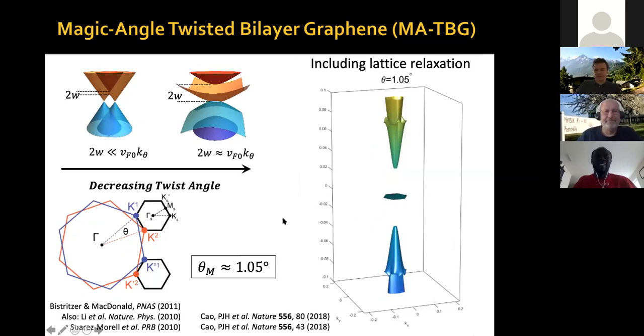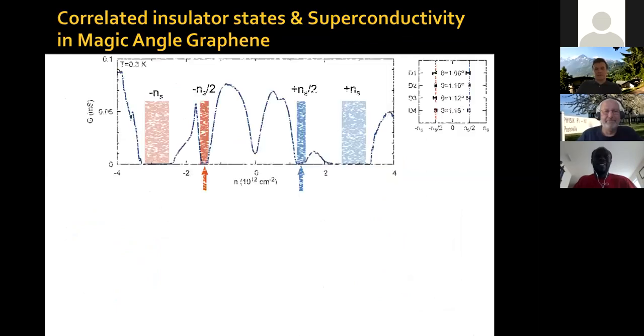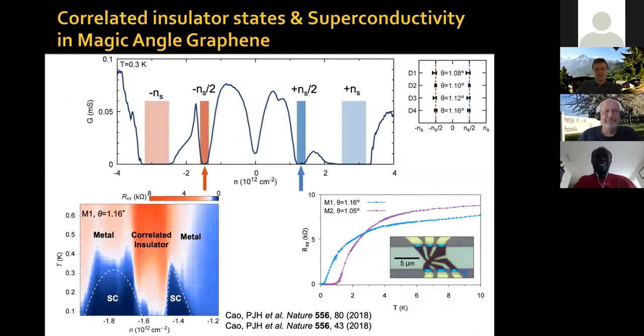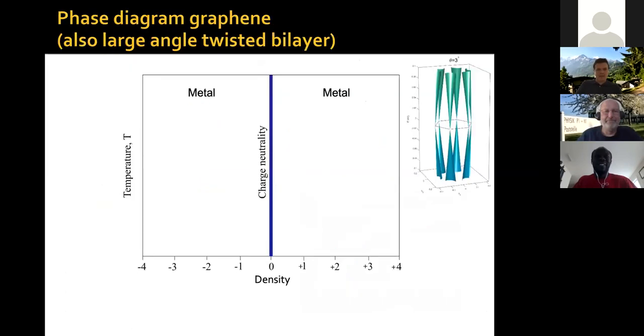And then after that, I mentioned yesterday that, when we fabricated our first devices at the magic angle, between two graphene sheets, we noticed the existence of these correlated insulator states when you put 2 electrons or 2 holes per moiré unit cell, and then superconductivity when you dope with extra electrons or holes nearby that correlated insulator state, okay? And this was the subject of yesterday's lecture. So I want to go back a little bit to the basics so that we can go deeper.